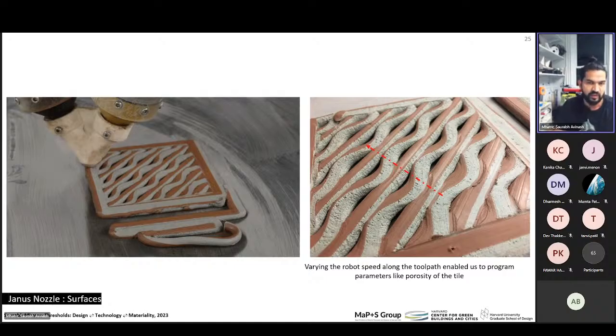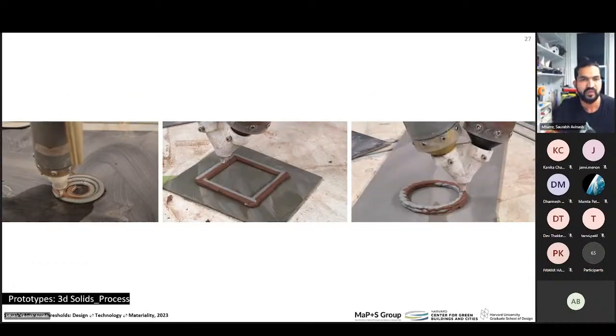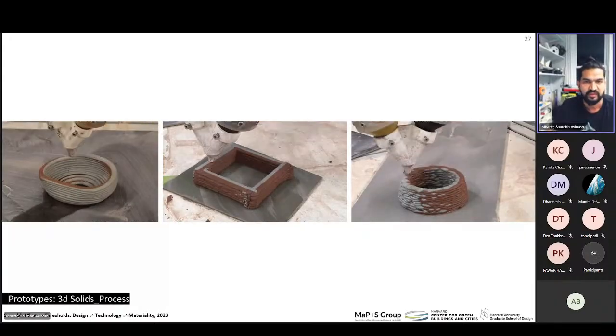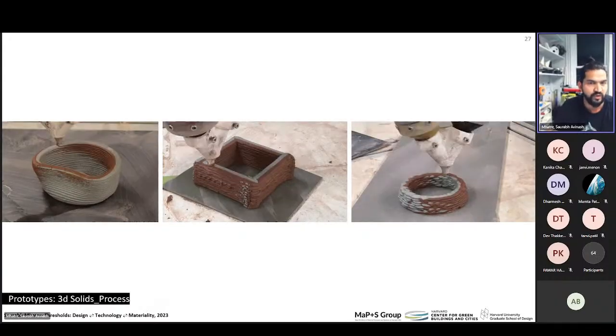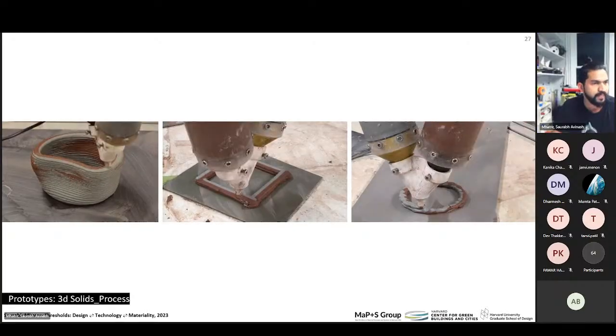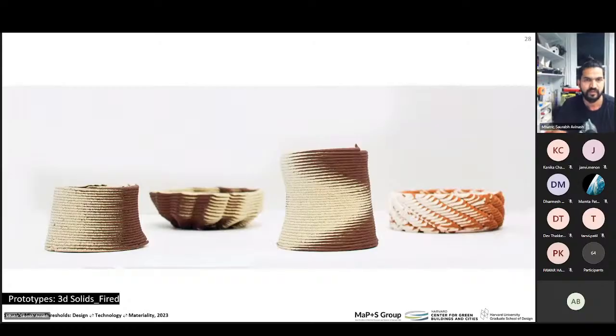For example, keeping all the parameters constant, increase in the robot speed reduces the width of the printed bead, and hence decreasing the robot speed increases the width of the bead. So in the right image, you can see that by adding slight increments to the robot speed, we got a decrease in the bead size. And because of the geometry, there was an increase in the level of porosity of the tile. We also experimented with three-dimensional objects where the toolpath was static and the nozzle orientation was dynamic, as well as 3D forms.